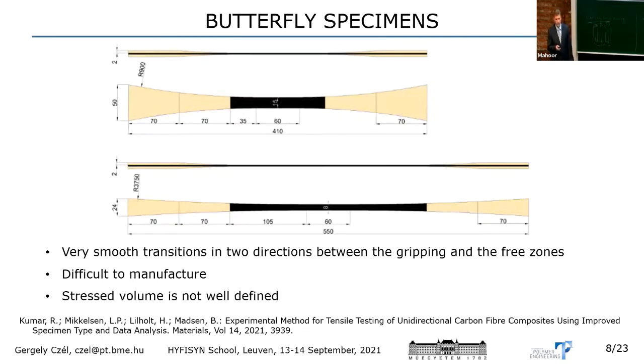And there is one more issue with this technique, is that the stress volume is not very well defined. So we can consider that part of this increased width zone is also stressed, and there might be critical clusters developing in this volume as well. But we need to reduce the strength, the average strength. So we can have different approaches to analyze the stresses and the volumes of the specimens, but this is just a little bit of a complication which can be dealt with.